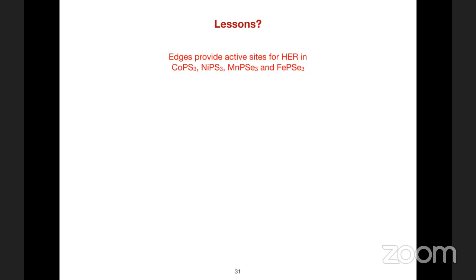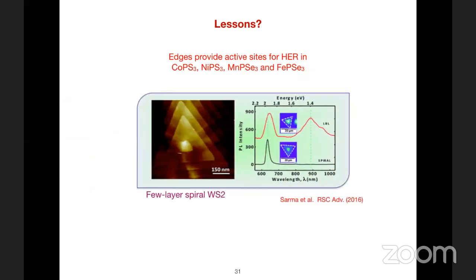The lesson is that the edges provide active sites for the hydrogen evolution reaction mechanism in these four systems. And that reminds us of work from Shaijimon's group in IISER Trivandrum, in which they were able to synthesize few layers of WS2 in a spiral structure. If you are able to synthesize these materials in a spiral structure, you would be exposing a lot of these edge sites. So our question and suggestion for the experimentalists would be, can these trichalcogenides be synthesized in such spiral structures so that their catalytic efficiency can be increased even further?